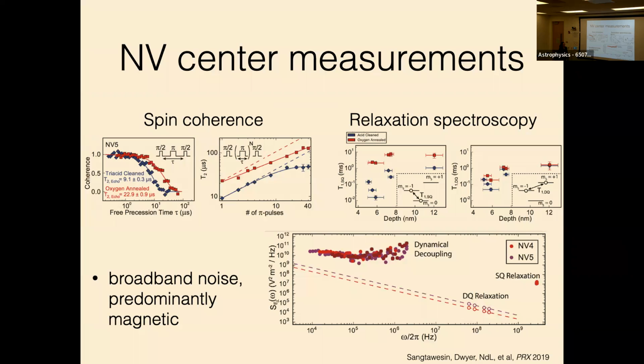We can also take advantage of the fact that the NV center is a spin 1 ground state and do relaxation spectroscopy. For first order, you can think of this as if I look at a single quantum transition where I go from ms equals 0 to either -1 or +1, you can drive that with magnetic fields, whereas changing the sublevel by 2 is not allowed by magnetic fields. So this is a probe of the relative electric field noise contribution versus the magnetic field noise contribution. And what we can see is that it's predominantly a magnetic field noise change because you get this big change in the single quantum T1, but a smaller change in the double quantum T1.